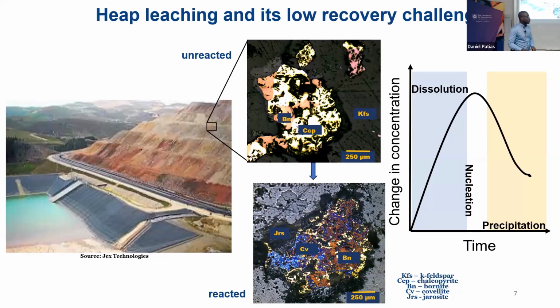So that's the whole cause, or one reason, that the industry has identified leading to low copper recovery. It's called passivation in hydromet literature. From a geochemical point of view, it's sometimes called surface armoring.